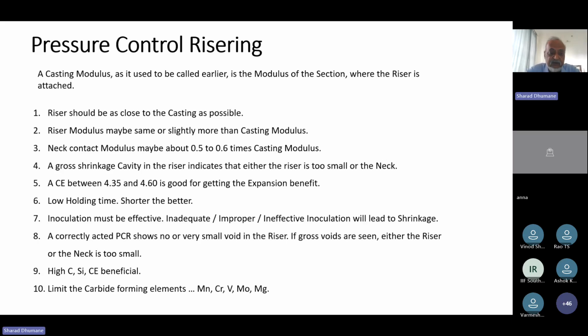Inoculation must be effective, no doubt about it, because all your graphite precipitation volume depends on how much you inoculate. So if inoculation is less, then you get lesser graphite, lesser expansion. If inoculation is more, your graphite volume will be more, expansion volume will be more. But after a certain point, you also run into shrinkage risk, as was mentioned by the paper which we saw earlier in the slide. So don't be on the lesser side, be slightly on the higher side, but don't go overboard.